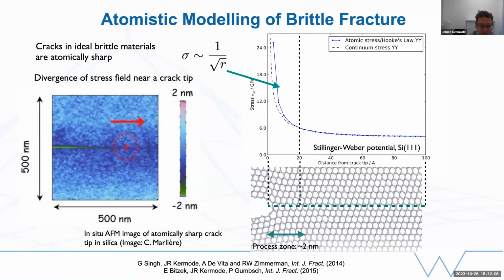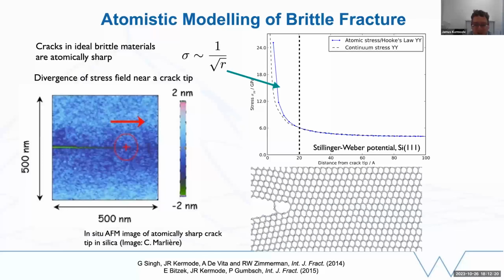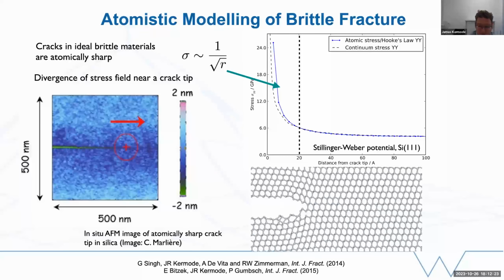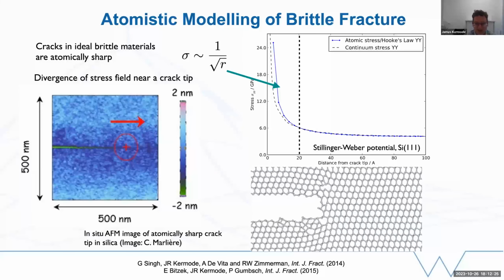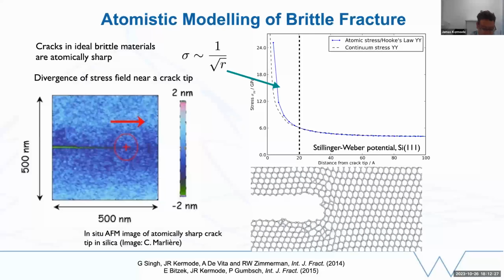So if we look at fracture, we have a divergence in a stress field. We have the stress going as 1 over square root r as we get close to the crack tip. This creates a nonlinearity and a process zone where there's complex processes taking place. And while we can capture the stress concentration well with a simple potential, the kinetics or the dynamics of fracture tend to be very badly captured.